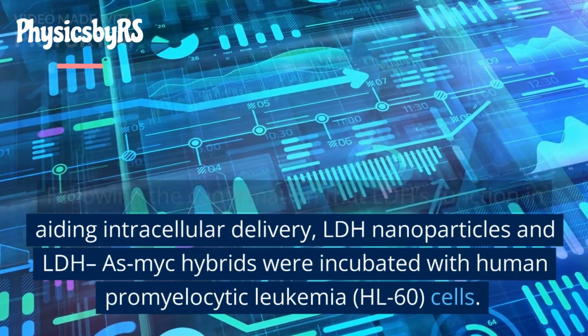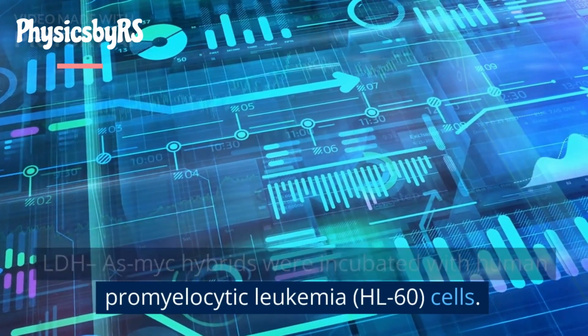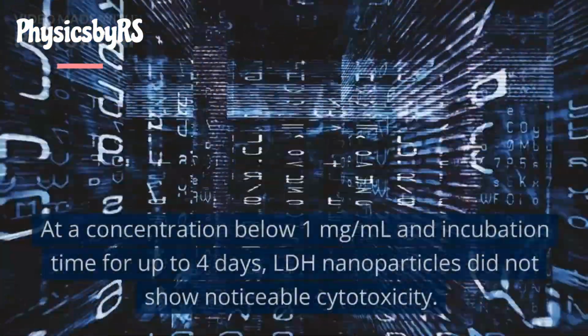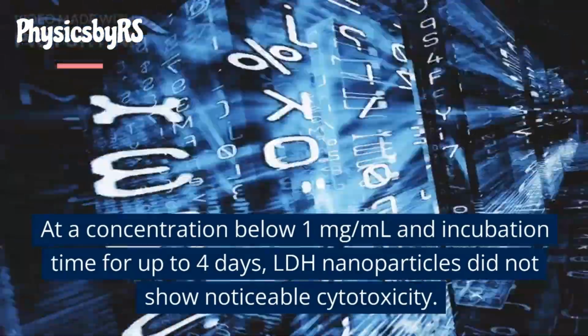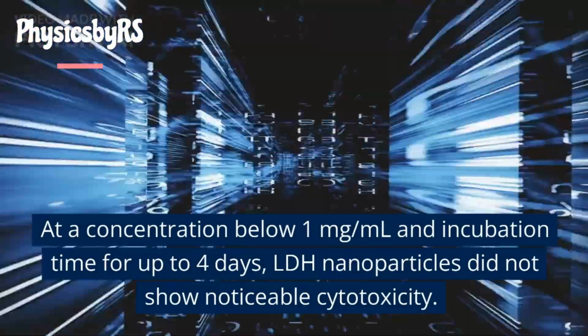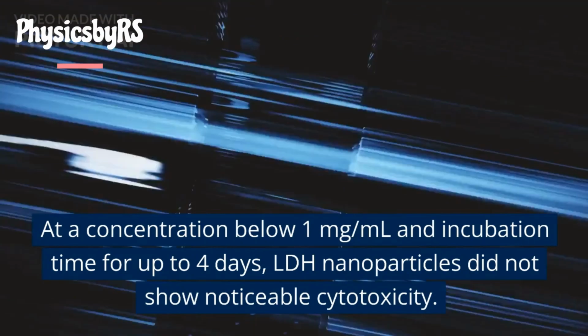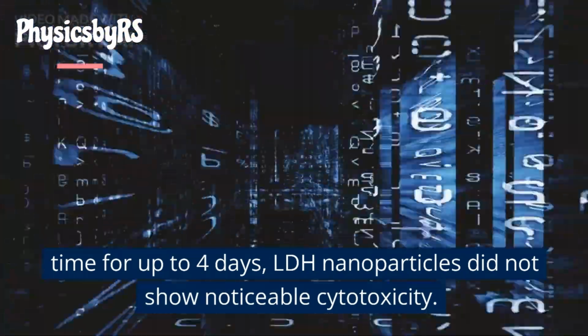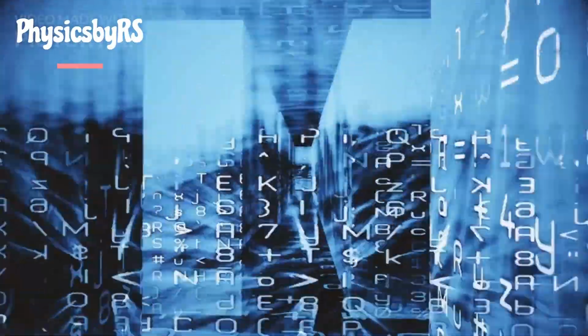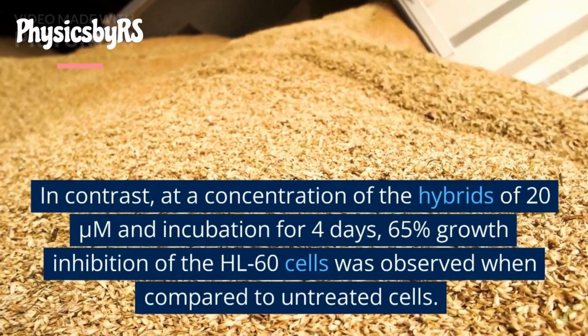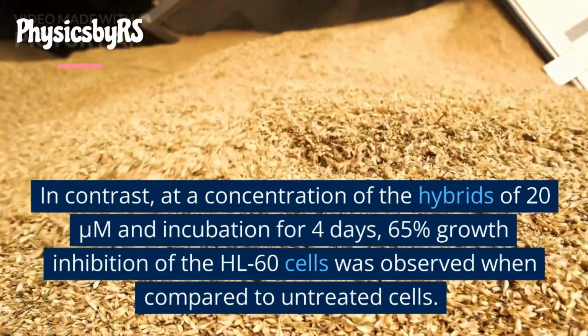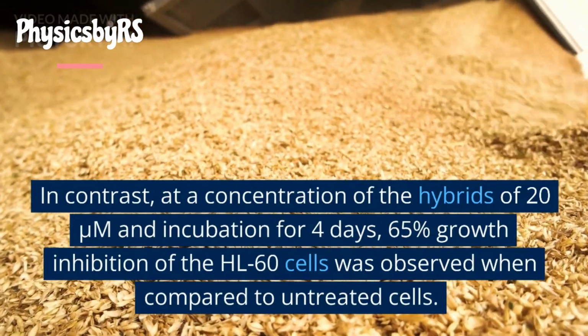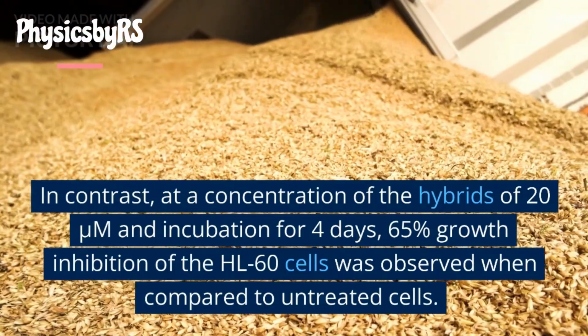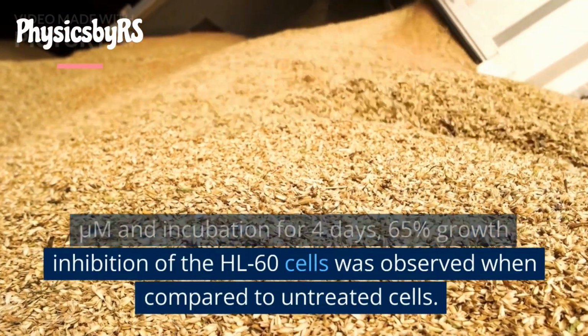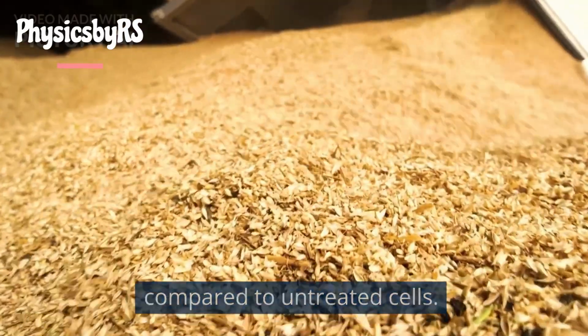Following the confirmation that LDHs function in aiding intracellular delivery, LDH nanoparticles and LDH-as-myc hybrids were incubated with human promyelocytic leukemia, HL60, cells. At a concentration below 1 mg per milliliter and incubation time for up to 4 days, LDH nanoparticles did not show noticeable cytotoxicity. In contrast, at a concentration of the hybrids of 20 μM and incubation for 4 days, 65% growth inhibition of the HL60 cells was observed when compared to untreated cells.